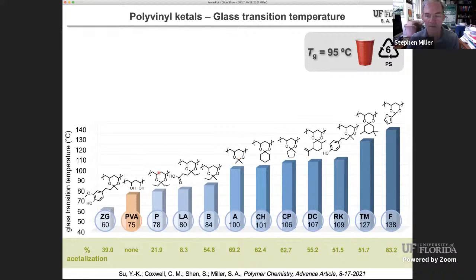And you can see that there are a pretty wide variety of polyketals shown here. There's a polyacetal hiding up there from furfural also, which incidentally gives the highest glass transition temperature. Zingerone's a little bit floppy, so it gives a glass transition temperature lower than PVA itself. And also you can see here the degrees of ketalization vary somewhat, largely in line with their steric bulk. Sterically bulky things just are a little bit hesitant to make those kinds of ketals.